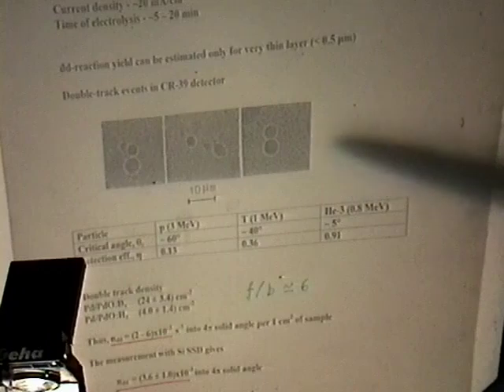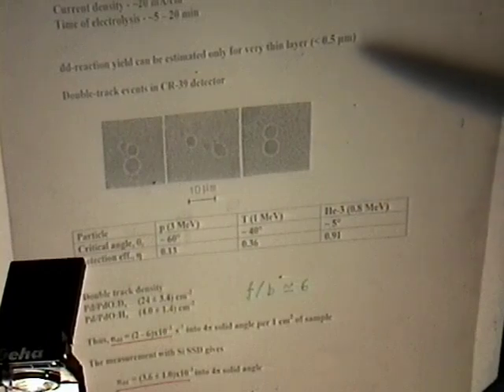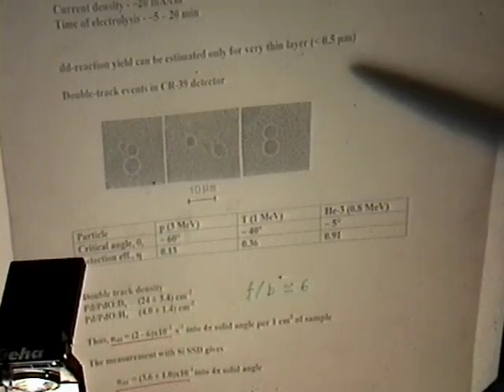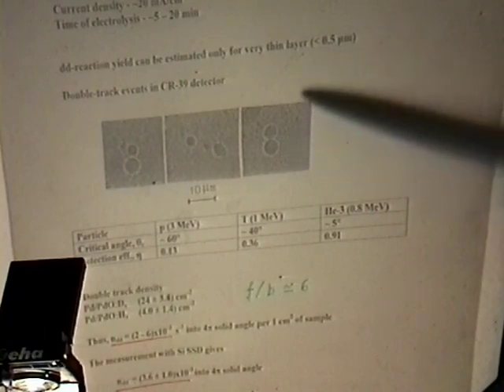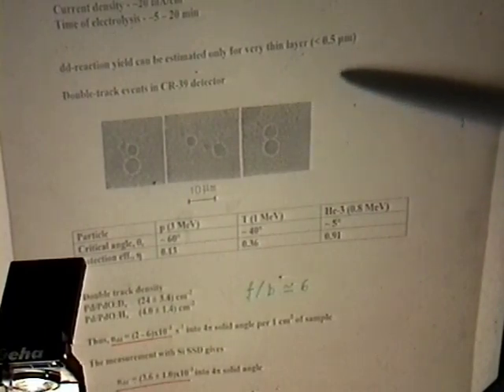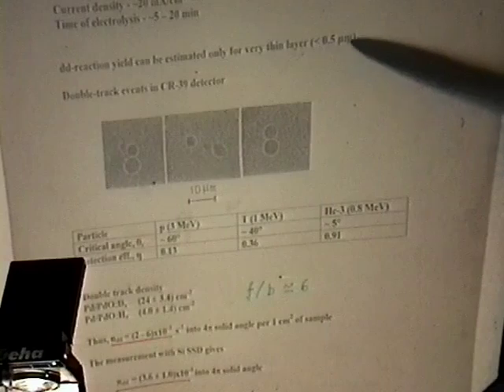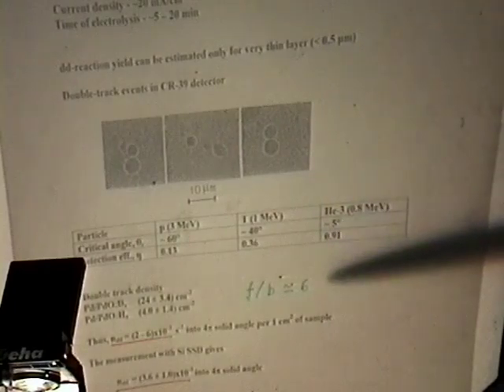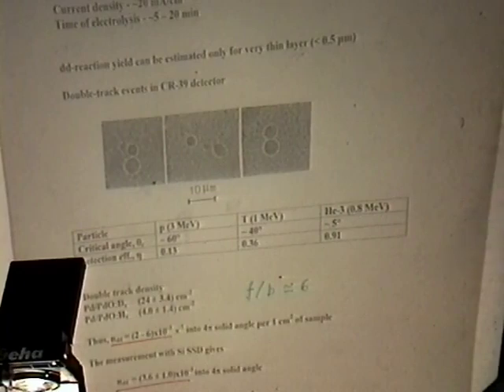We can estimate the deuterium reaction yield from the samples only for a very thin boundary layer, less than 0.5 microns, because this is a thick sample and reaction products outgoing from a thick sample may have very different energy loss.